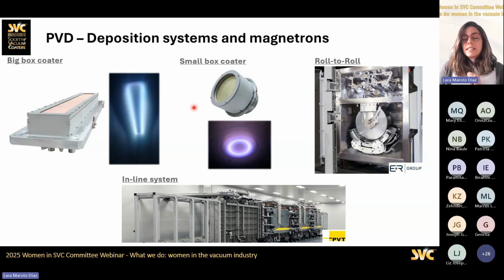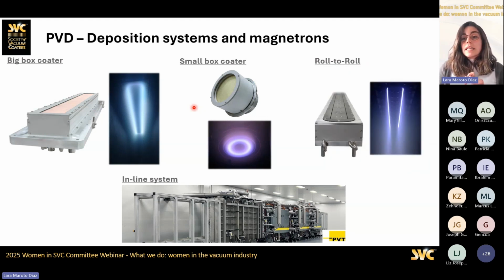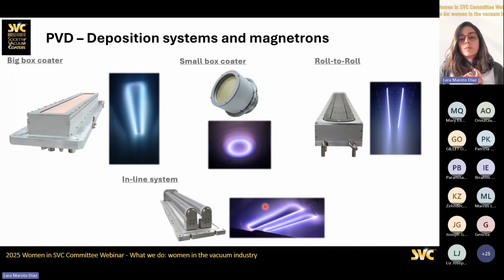For roll to roll, like Liz is going to tell us later, one of the big products used is the ion source. This is kind of the opposite of a magnetron. What we do is use ions to impact onto the substrate and clean it, for pre-treatment or post-treatment of the webs that are going to go through it. And then the inline system, this is to maximize throughput. You put the substrate at the beginning, and it goes through an inline system, all continuously coating, pre-treating, and then it goes out, so you have a continuous production. In this case, for example, some sources that can be used are rotatables. The target is rotating around, so what you maximize is target use, and you extend the target life.